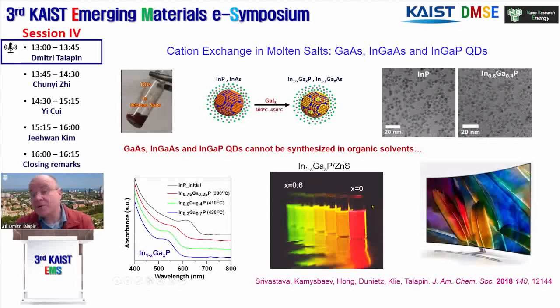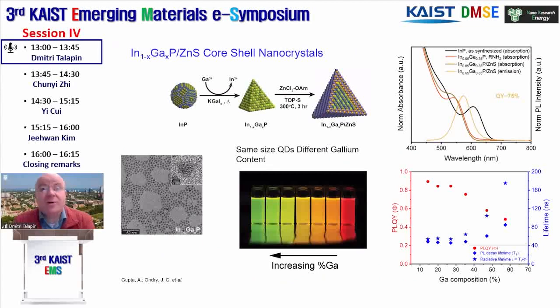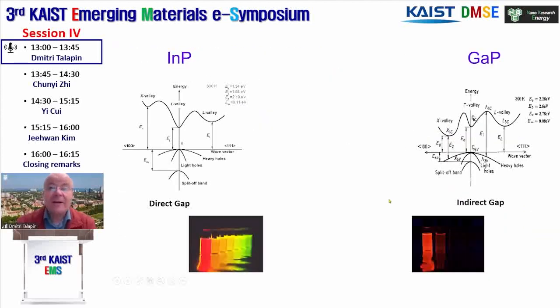The reason why these materials are interesting and important is that traditional QLED TVs are all serviced by indium phosphide quantum dots. And indium gallium phosphide is a more stable, thermodynamically more stable phase than indium phosphide. It also has a better lattice match to zinc sulfide. So that was a motivation for us to go after a better understanding of indium gallium phosphide core, zinc sulfide shell quantum dots, and we found that these materials can be pretty well engineered and optimized. We can make indium gallium phosphide quantum dots covering a very broad range of indium to gallium compositions with quantum yields of about 80% or so, which is pretty much on par with current indium phosphide quantum dots.